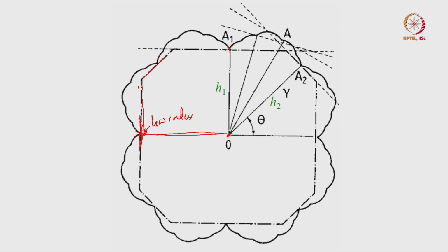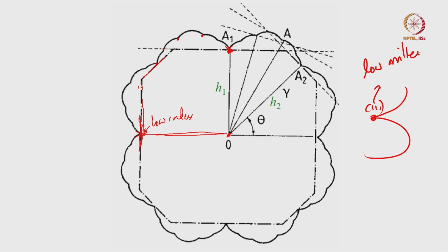Now let's take more realistic surface energies, though they look somewhat like this. There are all these surfaces with slightly lower energies, but there is a major low index surface here. The surfaces where there are cusps, typically in FCCs these are 1 1 1, are all low Miller index planes.